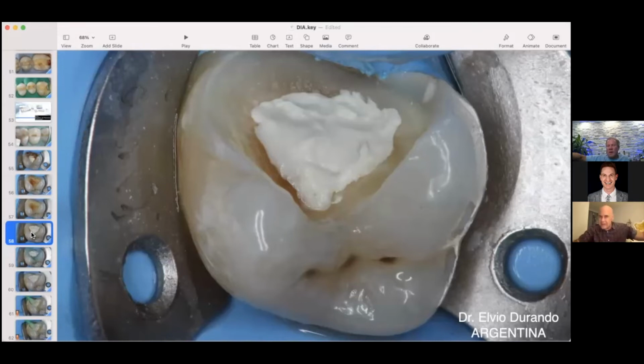Now you need compressive strength, you need different physical properties. So you need to be aware of that. And also, anywhere you put this liner, your bond strength is out. You can't think about bond strength and lining. They don't come together. You have the walls, you have the enamel, but deep down there, your bond strength is gone because you cover the bonded surface, which is dentin, with something, whatever it is. I think that's a really good point.